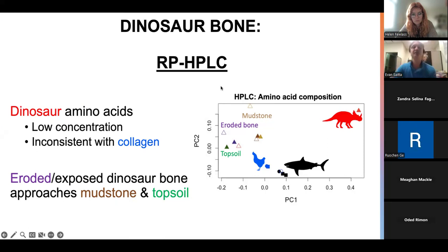Now, if we look at them with liquid chromatography, what we can see is that the dinosaur bones here in red are not only low in the concentration of their amino acids, but the composition of their amino acids is inconsistent with collagen. What you see in the younger modern bone in blue, or the subfossil teeth in black, the composition is very different from the aseptically collected Centrosaurus bone.